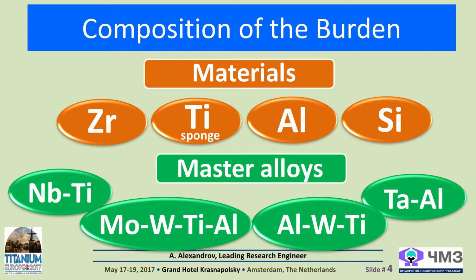The alloying elements having the largest content in the alloy are introduced as follows: aluminum, mainly in pure form and partly as a part of master alloys, and niobium as a part of Nb-Ti master alloy, with a niobium content of 50-55 weight %. The main attention was paid to minimizing the oxygen content in ingots, as the most harmful impurity affecting the processability of metal. The oxygen content was limited in this work by the requirement of not more than 0.06 weight %.